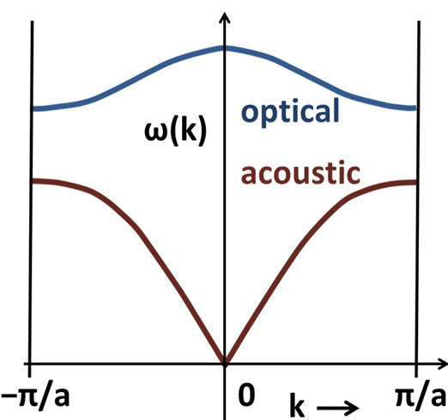Optical phonons are out-of-phase movements of the atoms in the lattice, one atom moving to the left, and its neighbor to the right. This occurs if the lattice basis consists of two or more atoms. They are called optical because in ionic crystals, like sodium chloride, they are excited by infrared radiation. The electric field of the light will move every positive sodium ion in the direction of the field, and every negative chloride ion in the other direction, setting the crystal vibrating. Optical phonons have a non-zero frequency at the Brillouin zone center and show no dispersion near that long wavelength limit.